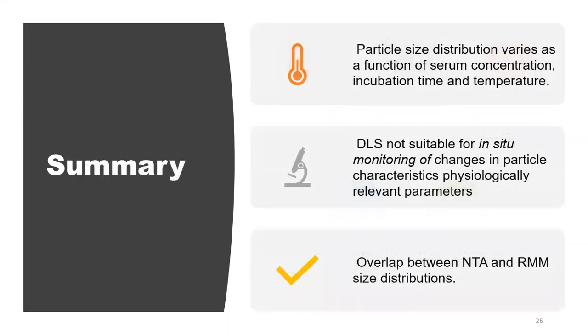So in summary, we're able to show that particle size distribution varies as a function of serum concentration, incubation time, and temperature, that dynamic light scattering is not a particularly suitable method for in situ monitoring of changes in particle characteristics at physiologically relevant protein concentrations, and we do indeed see and can demonstrate an overlap between the size distributions that we see for our particles via NTA and resonant mass measurement.